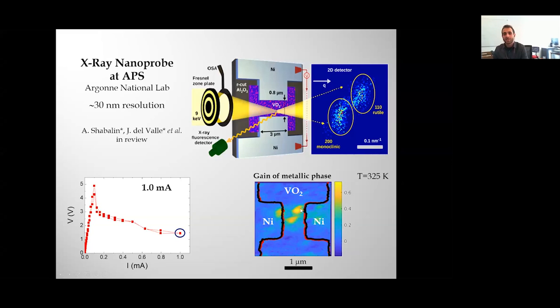In the video, you had this nice filament that was clean, percolating between both electrodes. But what you see here is that when you increase your resolution by a factor of 50 or 100, actually the picture looks very different. You don't have this clean percolation anymore. You have these spots that actually are the same size as the grains in your film. You have this heterogeneous percolation between the electrodes in your device.